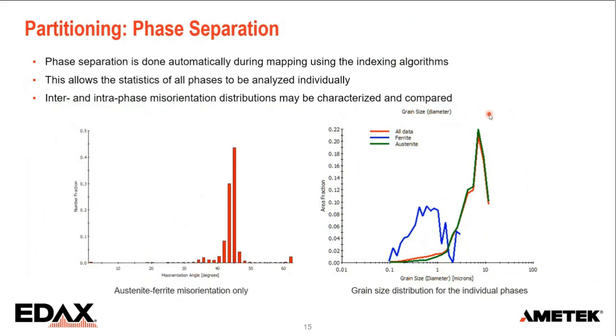The other thing you can do, once you have separated different parts of the microstructure, in this case the austenite and the ferrite, you can look at the interface between those components. So here it's just showing the interface between austenite and ferrite, showing the phase transformation relationship, which is typically around 45 degrees. But you can also do this between any subset that you can make.